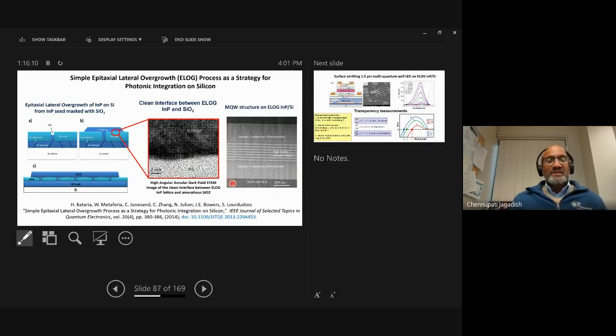I will not go into the details of these, but I was mentioning the dislocations. What people are finding is that you open a small nano slot here. If you're trying to grow indium phosphide on top of silicon, you create a mask, and the dislocations get terminated there. If you create this very thin area, it can grow further and then laterally grow, and in the process you're able to get very good quality indium phosphide or other semiconductors. For example, this is the work of Professor Sebastian Lourdudoss, working with Professor John Bowers and other colleagues. You can see they're able to show good quality indium phosphide on silicon with silicon dioxide masks. This is called epitaxial lateral overgrowth.